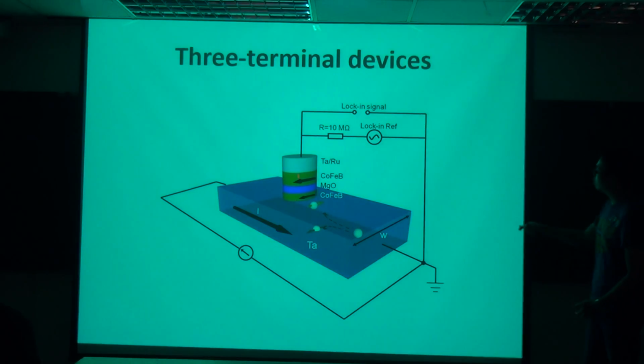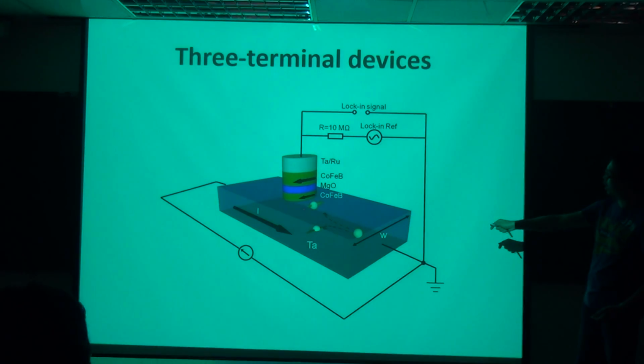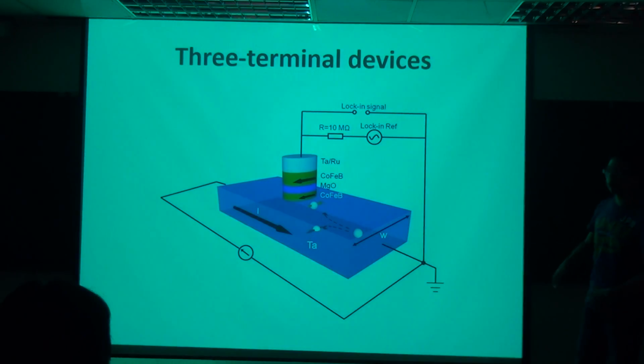And for the readout, you will measure the magnetoresistance change across this junction. So the sensing current will flow from here to here using a standard lock-in technique with a shunt resistor, and you will measure the change of resistance through the tunnel junction.